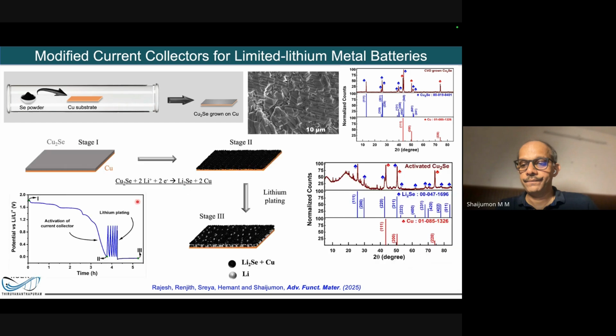And then what we do is we let it react with lithium. The moment it reacts with lithium, it forms a layer which consists of lithium selenide plus copper. That's the black layer that you see here. And that's where I talked about an artificial SEI layer, which is formed on top. My idea is that as you use this as an anode, the lithium is going to come, and this black layer is so lithophilic. It's so compatible with lithium because there is this Li2Se component, which likes lithium. So lithium comes through it nicely and gets deposited onto the copper, which is beneath. All my lithium is now very well protected because there is a top layer of this black layer, so further reactions will not happen because this black layer protects it.